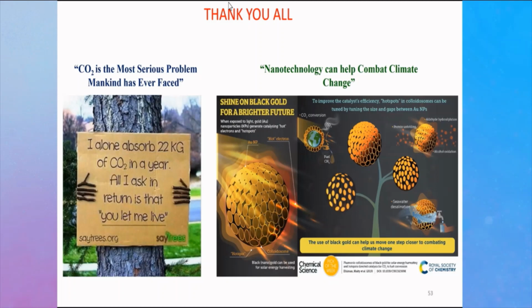I have difficulty understanding your question, but the concentration will ideally affect the kinetics of the reaction. CO2 is generally linear, very less reactive, extremely challenging to react. But as soon as it comes onto the catalytic surface, CO2 tries to bend, right? The bond angle changes, bond length changes. It's no more linear, it becomes reactive. And that decides the activation energy. That interaction of the CO2 with the surface decides the activation energy.